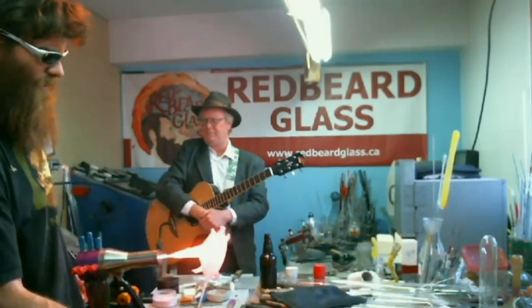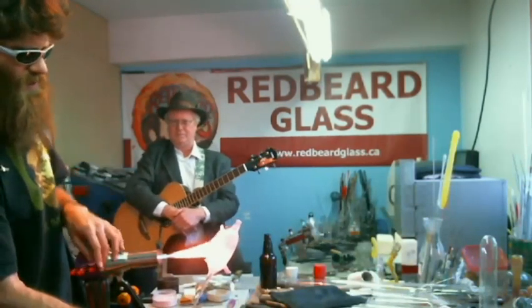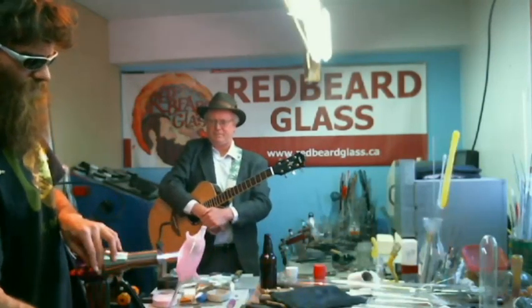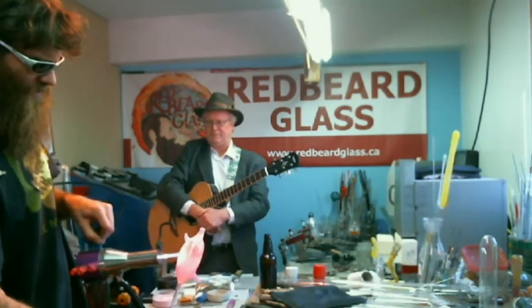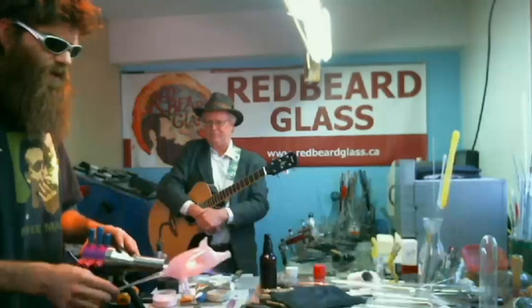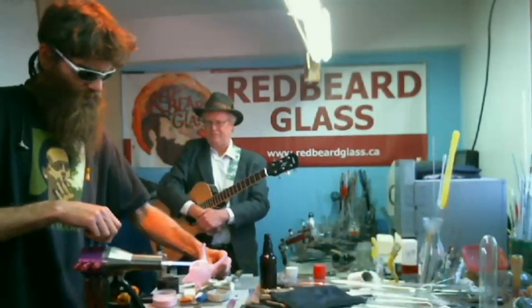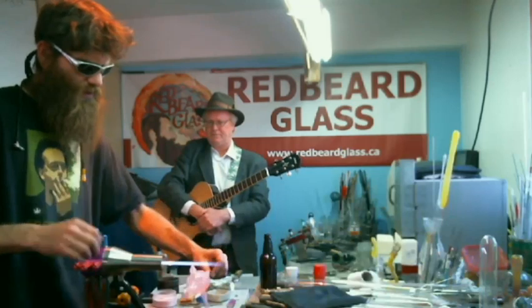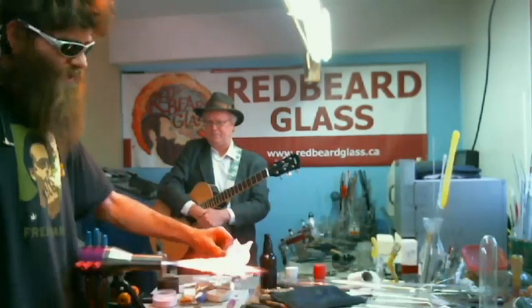So now we'll move up here. What we call this is chasing the crack. So you start at one end and you're just gonna work your way up. Change to a very fine needle point flame. As long as you've pre-warmed it, never go in with the needle nose first. It'll really bust open. So see how I switched to a bushy flame again?